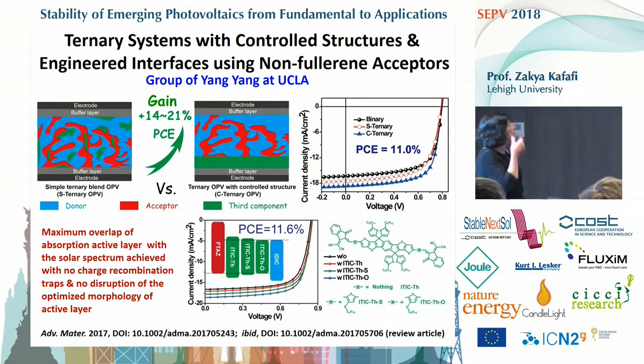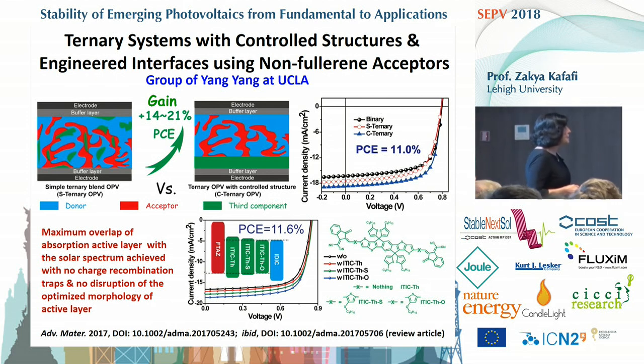So here is some of the progress that has been made on organic solar cells. This is the group of Yang at UCLA, where he has shown that, just by controlling the structure for a ternary blend, from having a very ordered structure, you can get a gain of about 14 to 21% in power conversion efficiency. So, going from a binary system to a ternary system with a controlled structure, you can achieve 11%. You can also tune and engineer the interfaces, and you can use non-fullerene acceptors for this. And he showed that we can achieve about 11.6% power conversion efficiency for these types of organic cells,